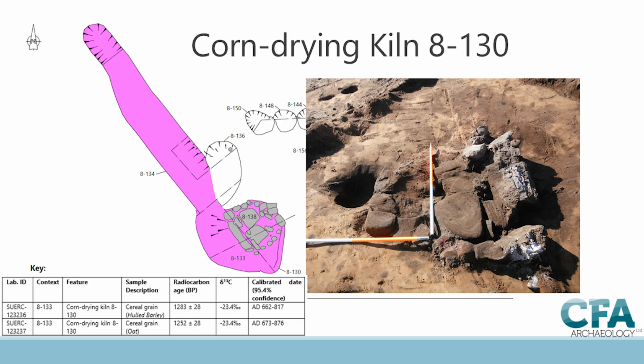So that kiln, which I was mentioning before, which is contemporary with this L-shaped enclosure, is located on the plateau, so the ditch is on the slope. This is at the plateau at the base of the slope. And the slope itself may have acted as a natural windbreak, which is why this kiln was here. There was no superstructure for the kiln, but there was the partial remains of a heat-affected stone surface.